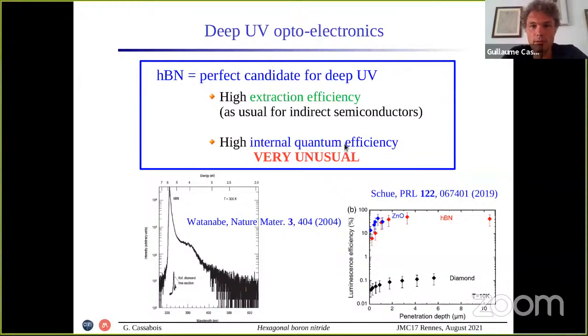This property was demonstrated in the pioneering work of Taniguchi and Watanabe in 2004. They compared HBN to diamond, two indirect crystals with approximately the same band gap. In the same setup, they observed more than three orders of magnitude increase of the signal in the case of HBN.